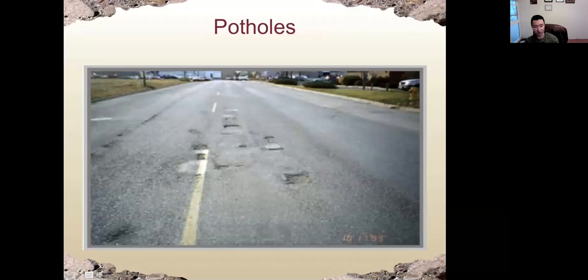And this is potholes. Everybody knows potholes. This is caused by fatigue cracking. Potholes only occur in thin asphalt pavement when the thickness of the pavement is only about 1 to 2 inches. So this is again a result of fatigue cracking of asphalt pavement. We have spalling off of a small piece of asphalt from the remaining pavement.